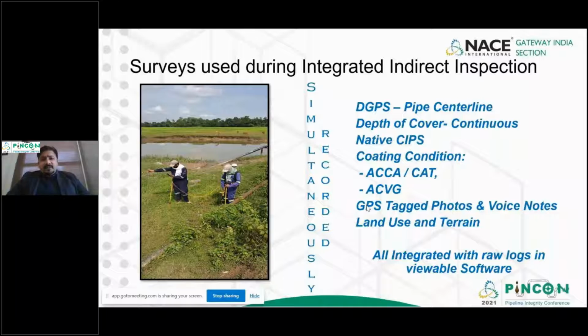So we are collecting GPS, we're collecting continuous depth of cover, which is also very important for ICDA programs. We're collecting native CIPS. It's not normal CIPS. Normal CIPS would have been in the case of CP protected pipelines. But in this case, we are collecting what the native potential is of the pipeline. That is what kind of potential is the line seeing from the environment as it is, without any in place impressed current cathodic protection or a sacrificial anode cathodic protection system.